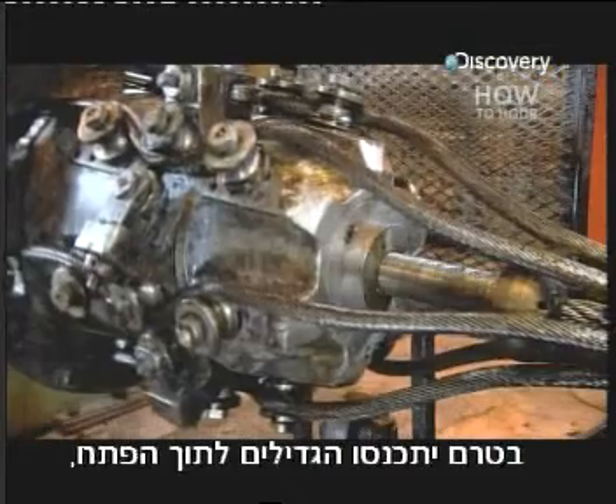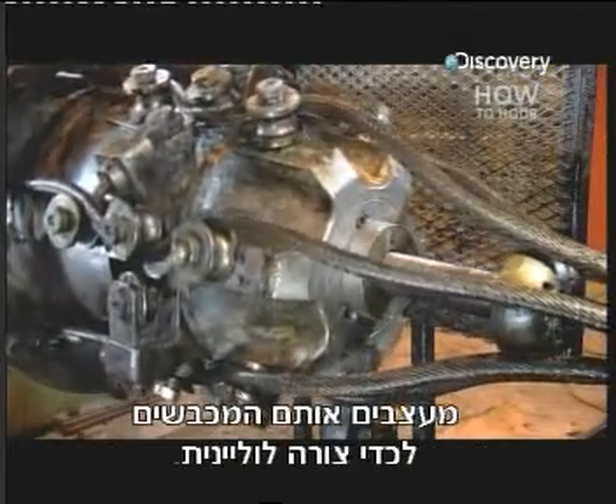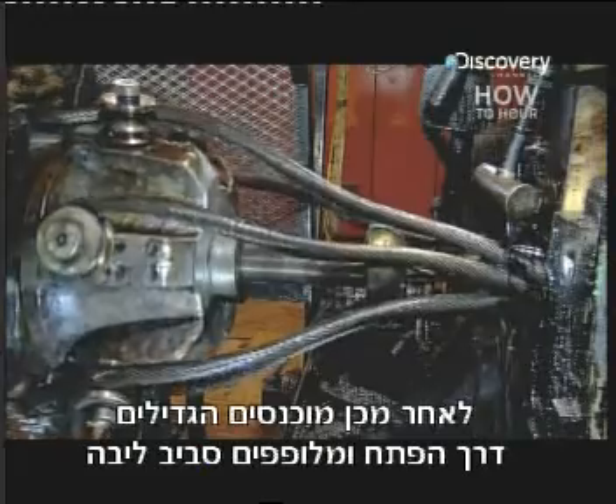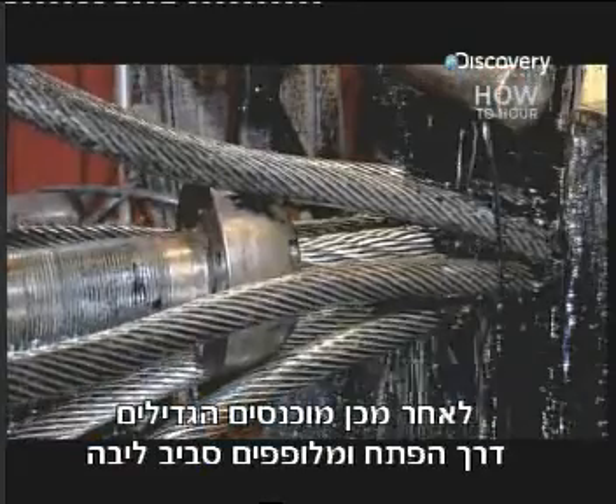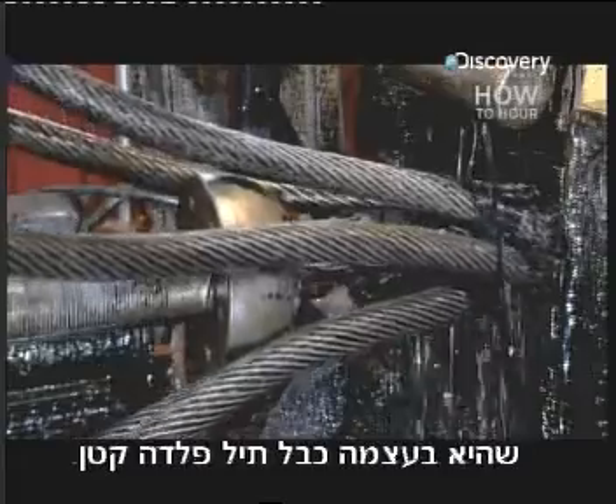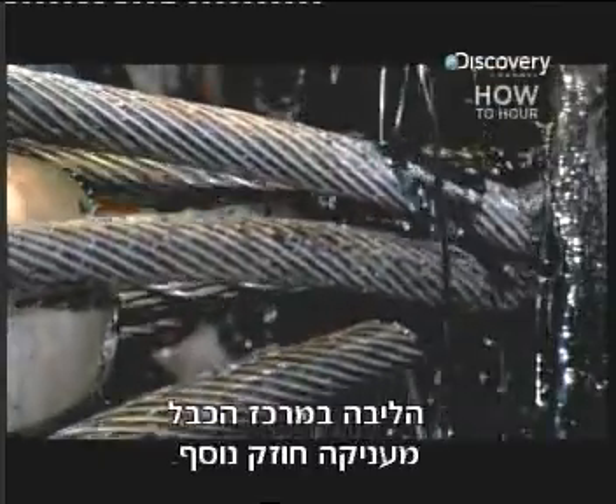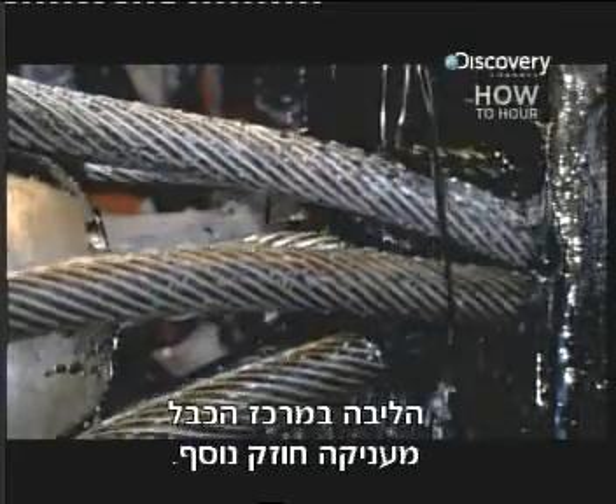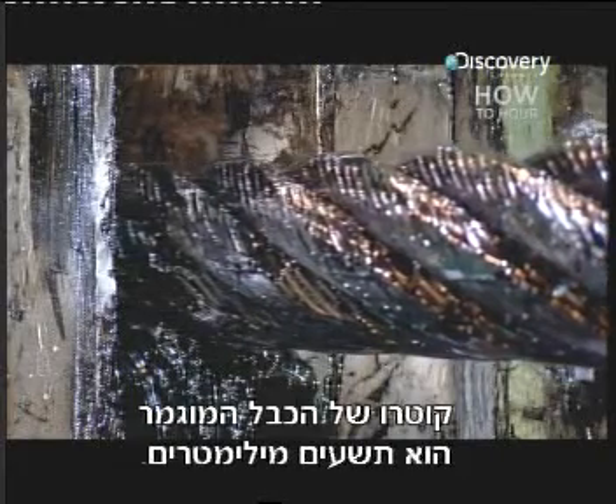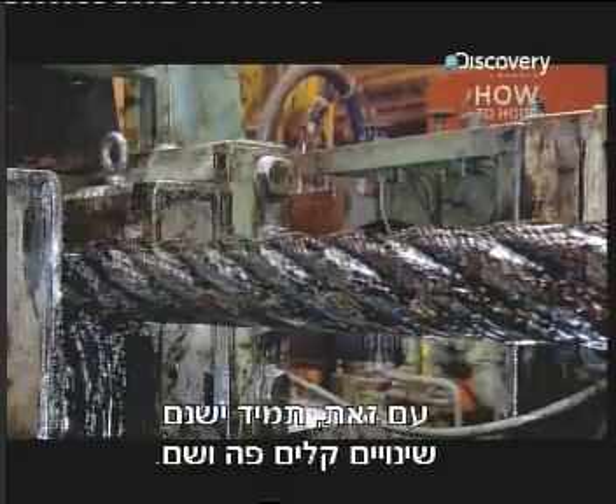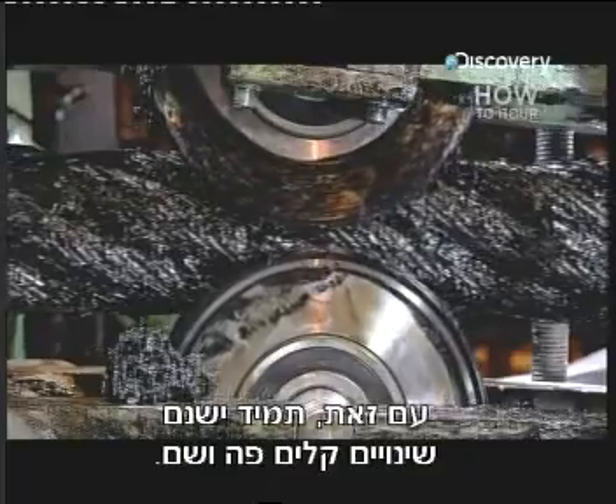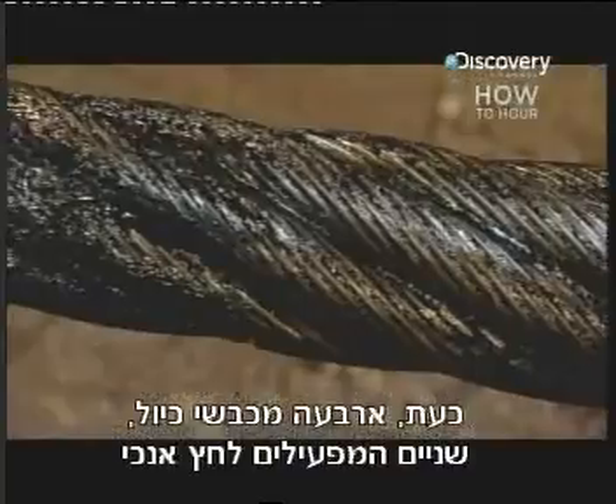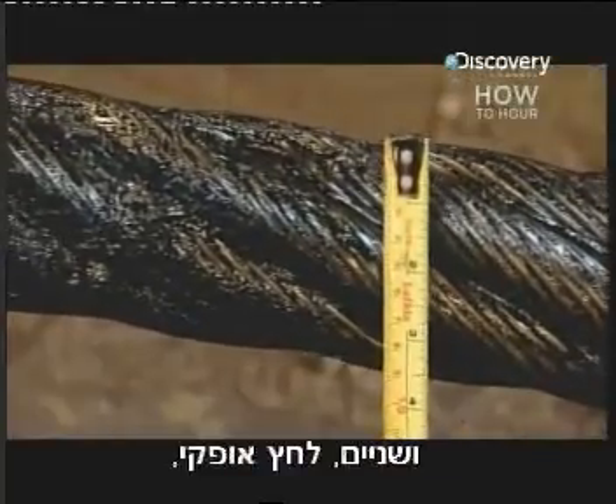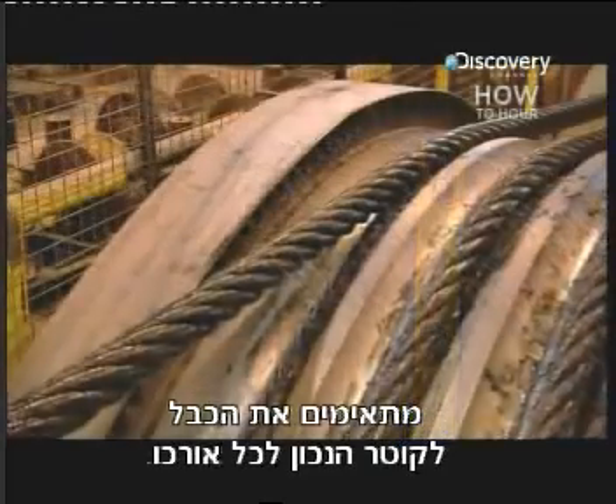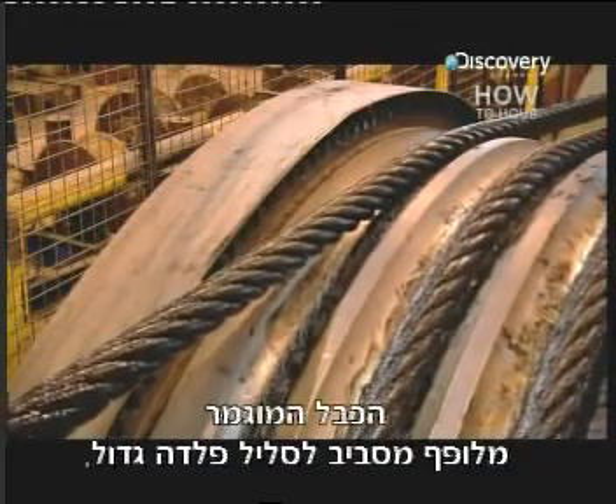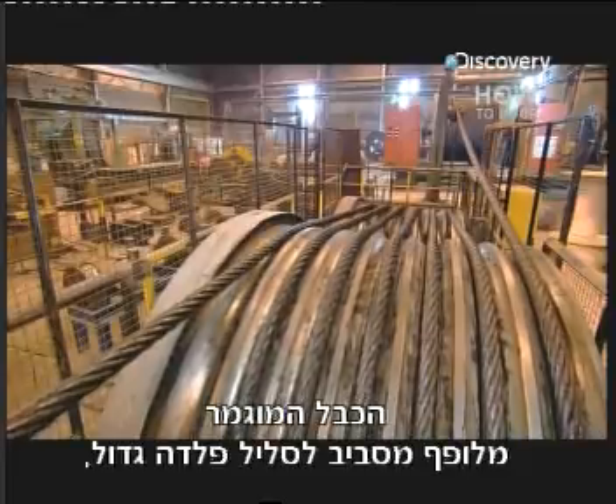Before the strands converge in the die, rollers pre-shape them into a corkscrew-like form. The strands then enter the die, twisting together over a core, which is itself a small steel wire rope. A core at the center of the cable provides additional strength. This cable's finished diameter is 90 millimeters. However, there are always small variations here and there. So now 4 calibration rollers, 2 compressing vertically, 2 horizontally, correct the cable to the right diameter all along its length. The finished cable winds onto a big steel reel, ready for shipping.